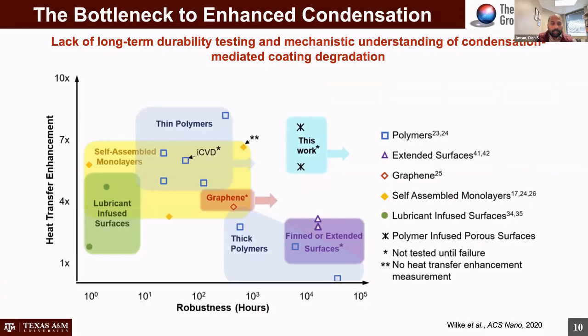So if we summarize, and I've taken this from literature, the different heat transfer enhancements and the timescale over which those heat transfer enhancements have been observed, you'll see that for different types of polymers, whether they're thin or thick, lubricant-infused surfaces, self-assembled monolayers, or these composite structures with metal nanostructures and polymer coatings, you see this wide range over which you can see heat transfer enhancement and robustness. And we started off with these self-assembled monolayers as they are the low-hanging fruit. But as we found out, it's a little more complex, as we always find out when we do research, that things are not as simple as they seem when you start out. And so what I'm going to talk about in the next few slides is our work with self-assembled monolayers, looking specifically at fluorosilanes and alkyl silanes.